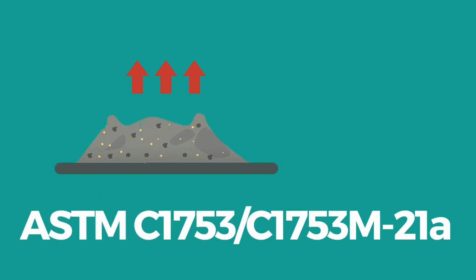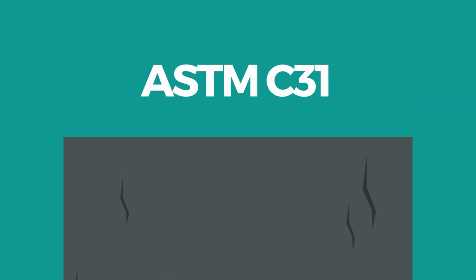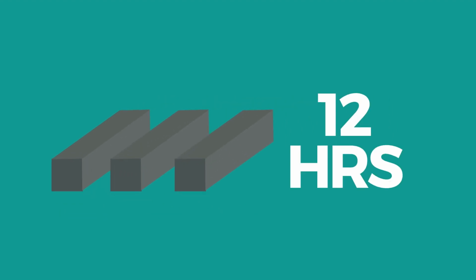In order to measure the sample's heat of hydration, procedures in ASTM C1753 or C1753M-21A will be followed. Samples for early age deformation will also be prepared following the ASTM C31 guidelines. Rectangular samples of the said proposed mixture designs will be prepared and stored 12 hours before the initial measurement. Its initial and final length will be measured 7 days apart.